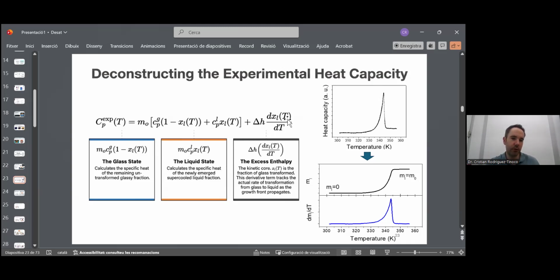Basically we have the contribution from the glassy state, the contribution from the liquid state, and the contribution of the change of enthalpy between the glass and the liquid, which depends on the temperature. So these are basically the two parts: this one on the right, the heat capacity of the glass and the heat capacity of the liquid, plus this contribution here, which is from the enthalpy of the vitrification. So this plus this is basically the experimental measure.